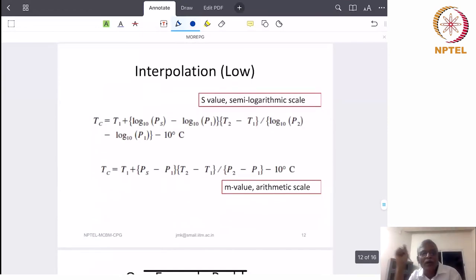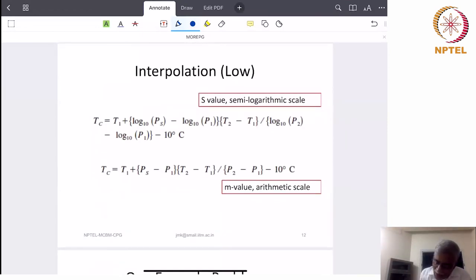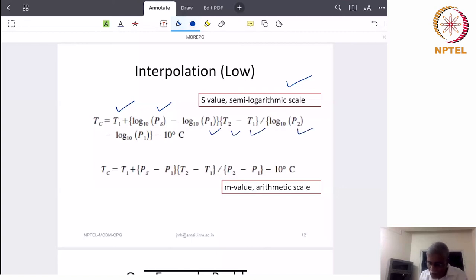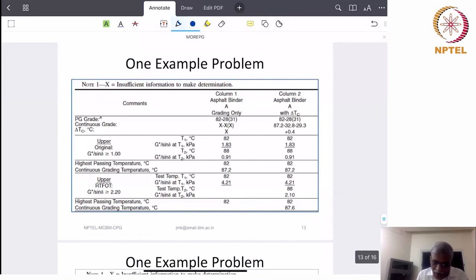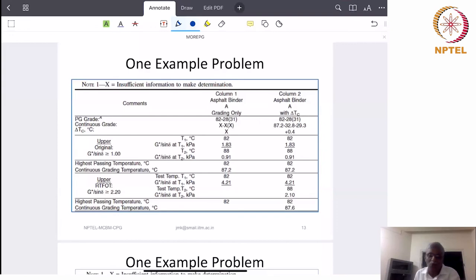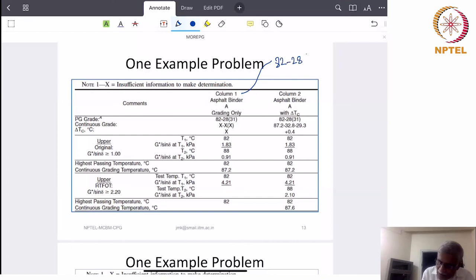For the low temperature S value, the same formula is used but in a semi-logarithmic scale. T1, T2, Ps, P1, and P2 have the same meanings. For the M value, the interpolation is done in the arithmetic scale. Now let us look at an example problem. Wherever there is an 'x' given, there is insufficient information and additional data must be collected. Let us assume we have a binder like this: 82 minus 28 (with minus 31 in brackets). So 82 is the high temperature, minus 28 is the low temperature, and minus 31 is the intermediate.